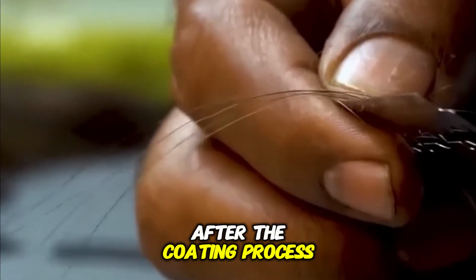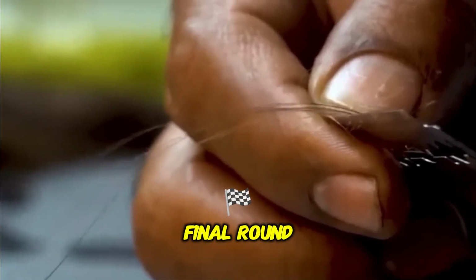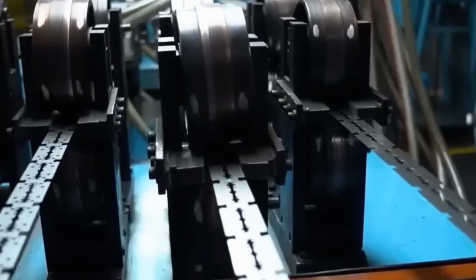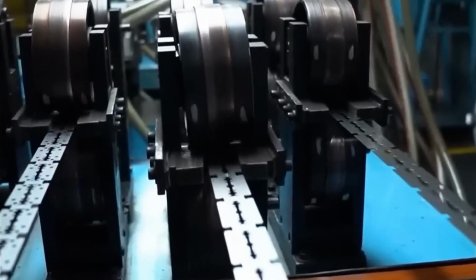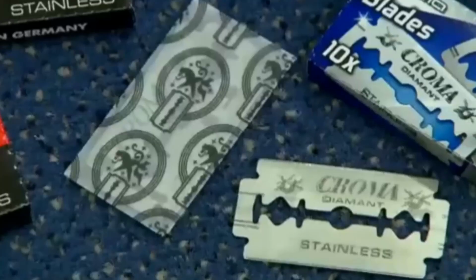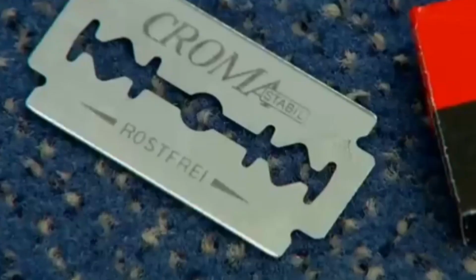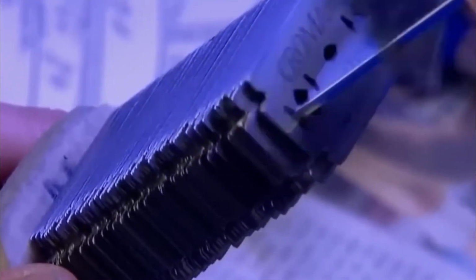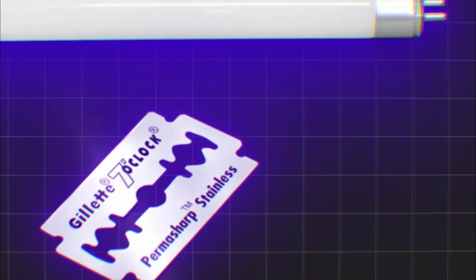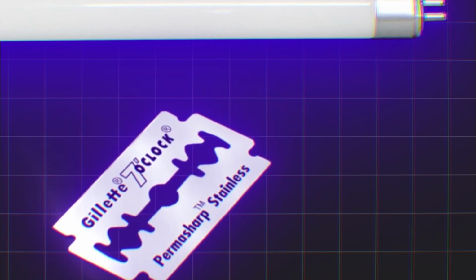Final testing and durability checks. After the coating process, the blades undergo one final round of quality control. Technicians measure the strength of the blade by testing its ability to cut through a thick bundle of wet paper. This test ensures that the blade meets the required strength and sharpness specifications. Another key test involves checking the blade's cutting ability after it has been coated. The coated blades are then tested to ensure they retain their sharpness and cutting performance even after the coating process.